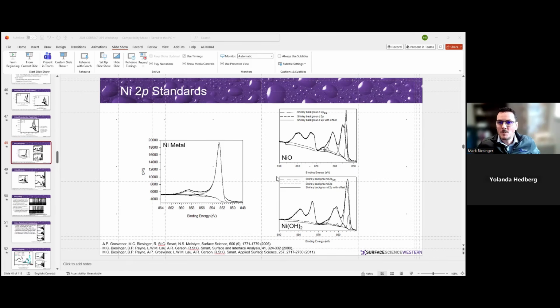And so to do small spot analysis, they focus the X-rays down into a smaller and smaller spot. And so you're still getting a lot of photoelectron flux from that smaller spot. And so it's much better at taking that small spot analysis. You'll get much stronger signals. So it's just a different configuration of the instruments.